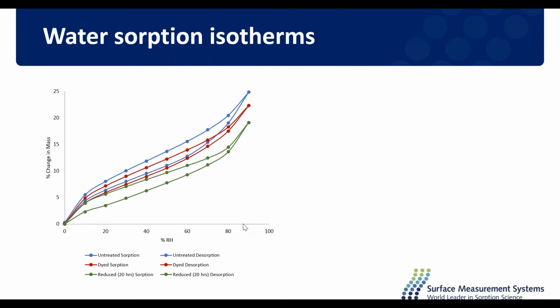It suggests that actually, while we've been reducing that crosslink content, it's the additional hydrophobicity imparted by the methylation and also by the additives in the hair dye formulations that plays a much stronger role in total water sorption capacity rather than crosslink density. As you would expect, fibres with reduced crosslink density are able to swell better and absorb more water. So that was a really interesting thing that we found here.